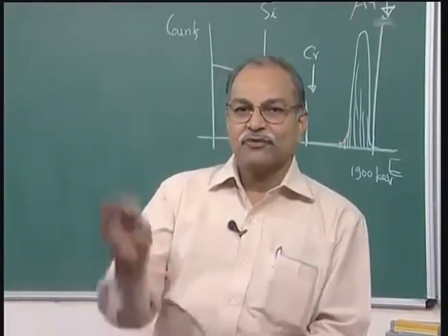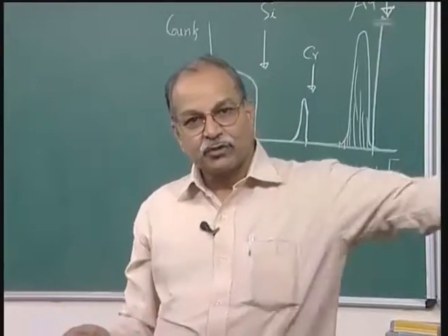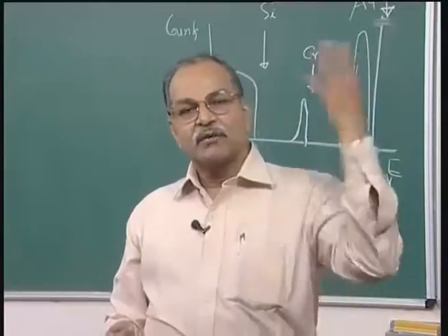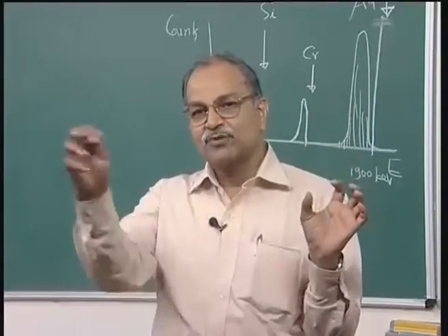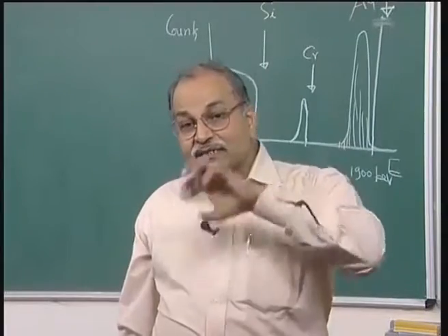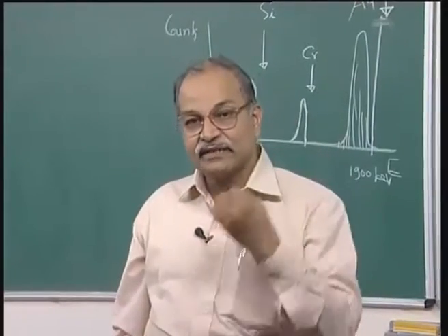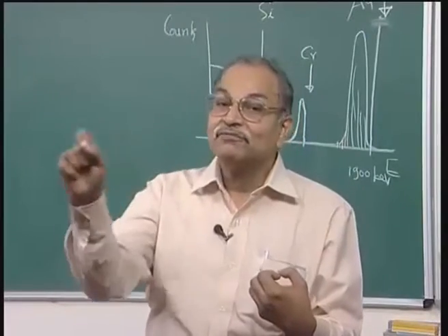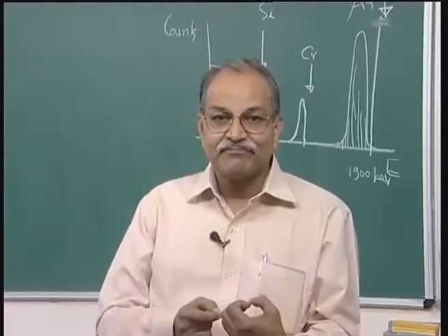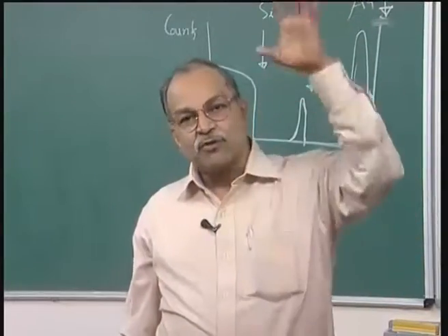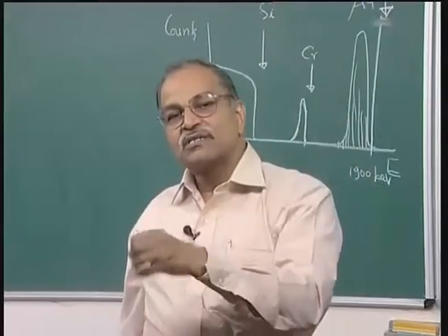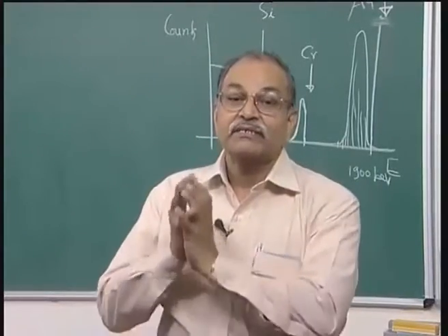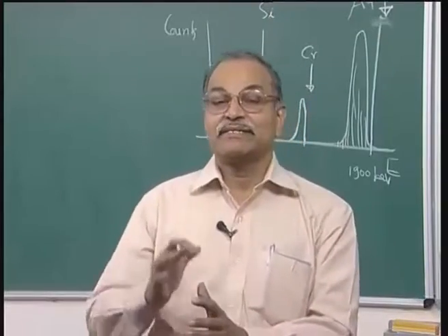So, in one go, if you have some 3, 4, 5, 6 types of impurities, this proton beam goes and interacts with those atomic electrons, and K alpha and K beta and L alpha and all those X-rays are emitted from those elements, and those X-rays will be detected with their energies, and from the energies of those X-rays we will know what kind of elements are sitting there from which these X-rays are emitted, and from the number of counts at that energy level, or the area under the peak, we will know the amount, the concentration, how much of which impurity is sitting there.